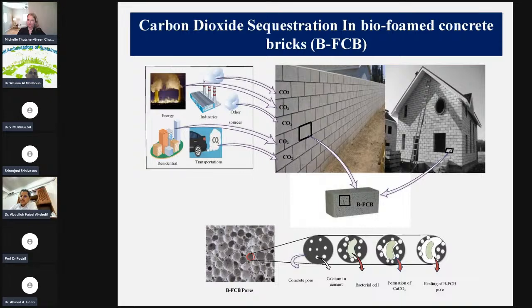If we use a concrete brick and zoom into a part of the concrete, we can see the porosity. If you see the foam concrete here, there is a lot of porosity. If we zoom into the pore, what we will find in the pore is the void and calcium because of the cement. Now we are trying to use a new technology. We are using bacteria inside the concrete.